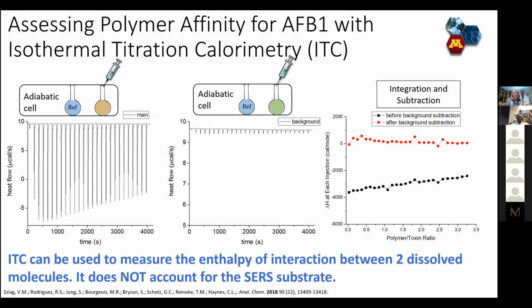And so you're looking at 2 sample traces here where we've measured ITC heat exchange. On the left is one where we have polymer and aflatoxin. In the middle is a control, so there's no heat of interaction because there's nothing interacting. And then we can essentially plot, as you see on the right, the delta H for each injection and characterize how strong the interaction is between 2 things.